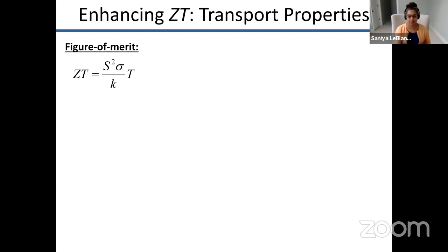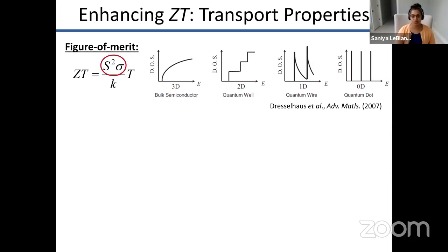If we look at the figure of merit for thermoelectrics, the numerator of this tells us about what's happening with electrons in the material. So you want this figure of merit to be larger, you want the numerator to be higher, so you want a high Seebeck coefficient, high electrical conductivity. And then one of the really interesting findings has shown that if you nanostructure the material, you'll change what's called the density of states, which is where electrons can be in the material. And changing that density of states actually allows you to increase this numerator. Primarily, you can have a significant change in the slope of the density of states, and you can increase that Seebeck coefficient.